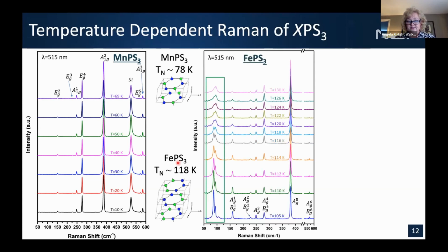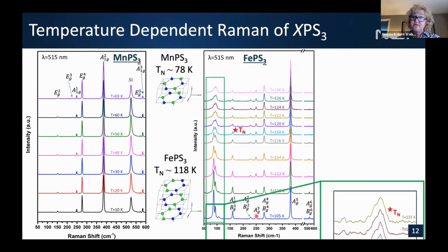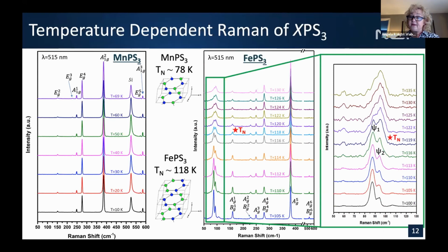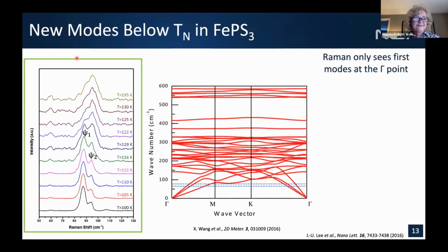Then if we have a look at the iron PS3, we're able to highlight quite a bit of difference in this low frequency region. Again, this had been seen by the Korean team. And here is the transition temperature at about 118, the Néel temperature transition. What you're able to see is a rather unstructured feature become quite sharp and able to resolve that feature as the temperature decreases. If we decrease the temperature even further, I'm sorry because my face is over this part of the spectra. We are able, here we go, to see as we go from 135 down to 100, we're definitely resolving two features.